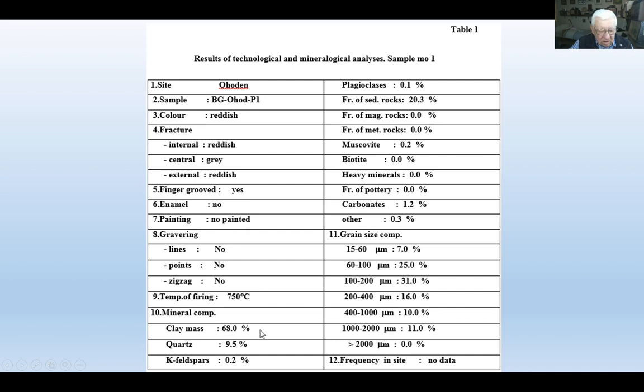Terra rosa is a secondary sediment developed on limestone due to weathering of limestone. This clay composite, terra rosa, is composed of poorly crystalline kaolinite — very good for preparation of pottery. There are small admixtures of quartz, feldspars, and fragments of sedimentary rocks, mostly fragments of limestone, and traces of secondary carbonate, fragments of charcoal, and other rare components.